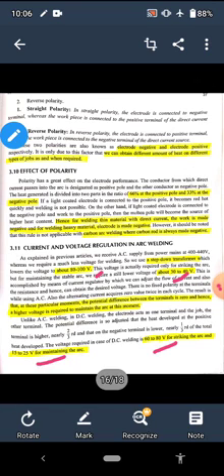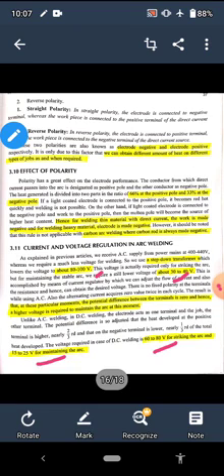In case of AC arc welding there is no fixed polarity at the terminals because after every half cycle the polarity changes. The alternating current acquires zero value twice in each cycle, so at those particular moments the potential difference between the terminals is zero, and hence a higher voltage is required to maintain the arc. To summarize: for AC arc welding, striking the arc requires 80 to 100 volts and maintaining requires 30 to 40 volts; for DC arc welding, striking requires 60 to 80 volts and maintaining requires 15 to 25 volts.